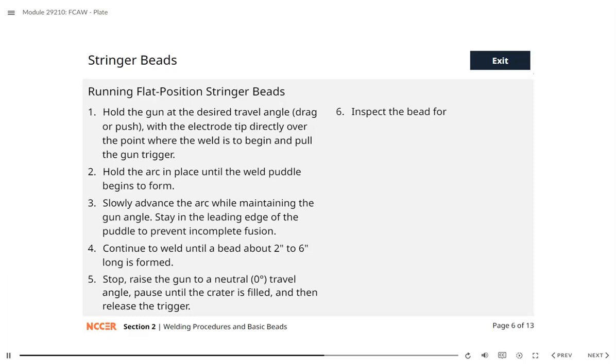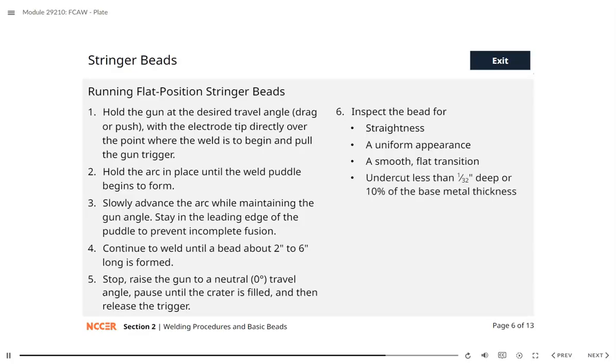Step 6. Inspect the bead for straightness, a uniform appearance of the bead face, a smooth, flat transition with complete fusion at the toes, and undercut less than 1/32 of an inch deep or 10% of the base metal thickness. Also, check to ensure that there is no excessive porosity, overlap, pinholes, inclusions, craters, or cracks.